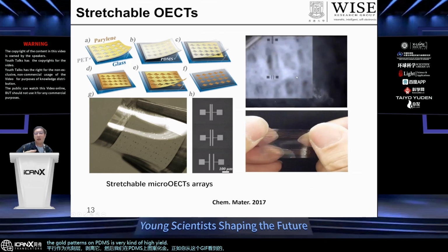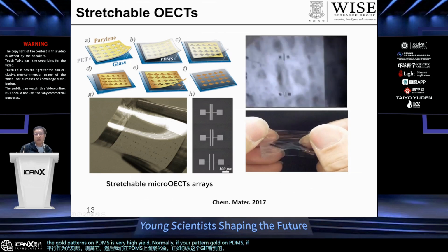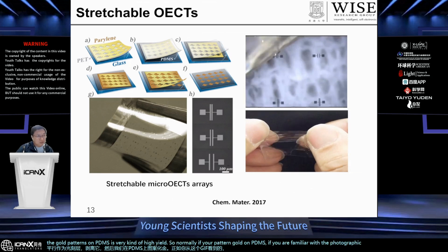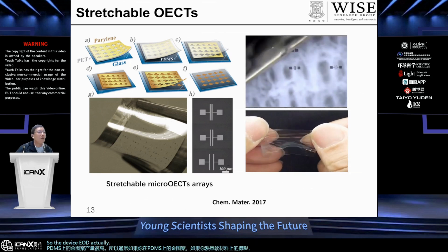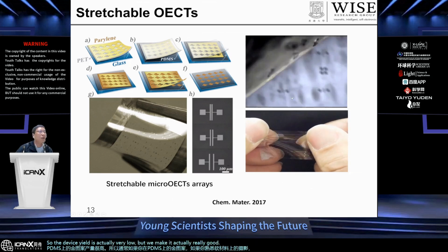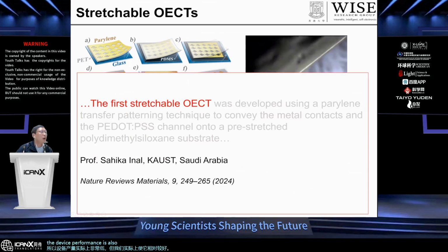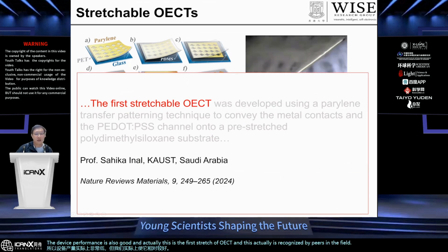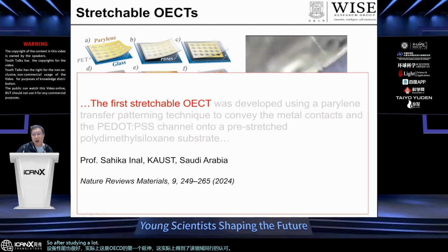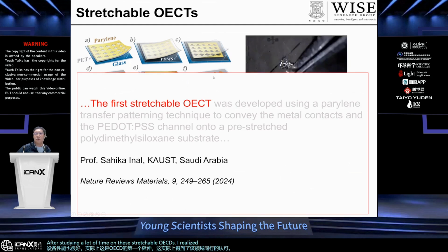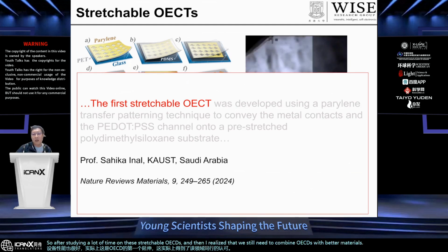Normally if you pattern gold on PDMS, if you're familiar with photolithography on soft materials, the device yield is very low, but we make it relatively good. The device performance is also good, and this is the first stretchable OECT, and it is recognized by peers in this field. For example, this is a paper recently published. After studying these stretchable OECTs for a long time, I realized that we still need to combine OECTs with better materials that have better tissue-like properties.